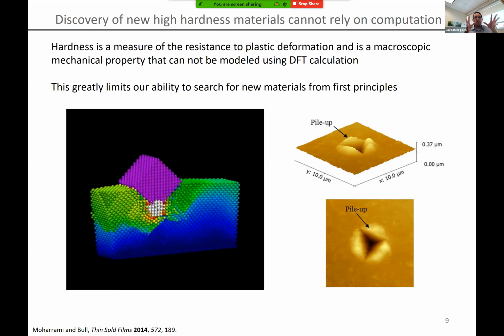As the atoms move out of the way, they undergo significant amounts of what's called pileup, or maybe closely related to things like surface reconstruction. And you'll see with this surface reconstruction that even in the molecular dynamics simulation, this is not well captured. So we can't cover the length scales necessary with DFT, and we certainly can't cover the surface reconstructions necessary at the DFT level.